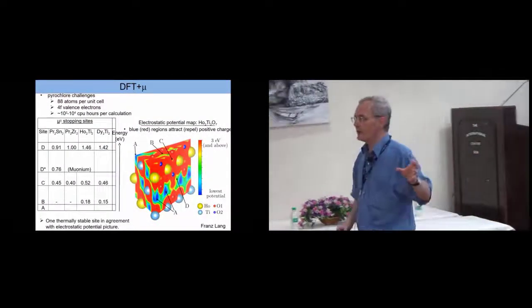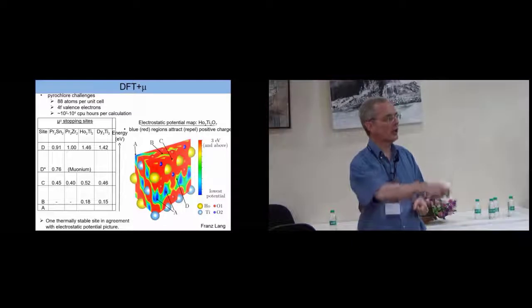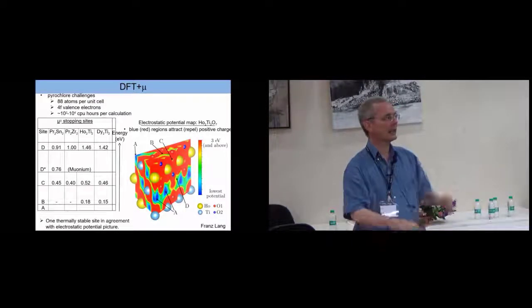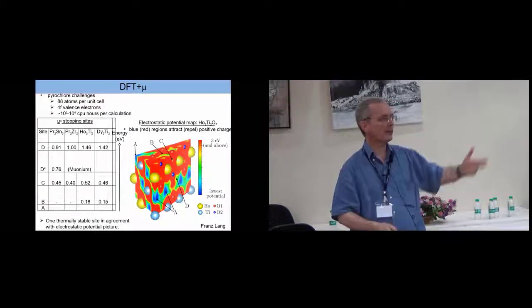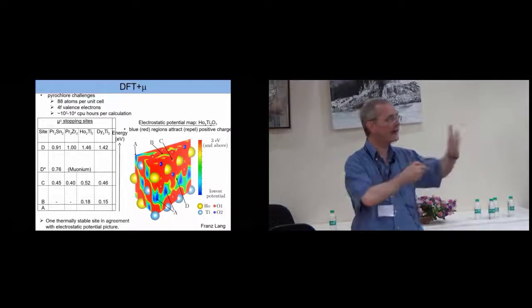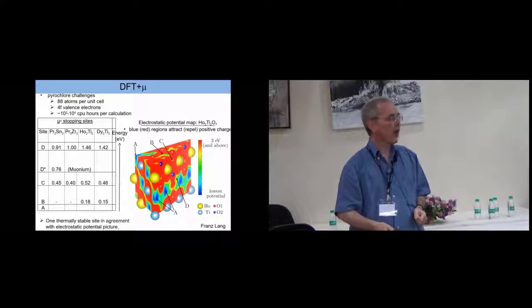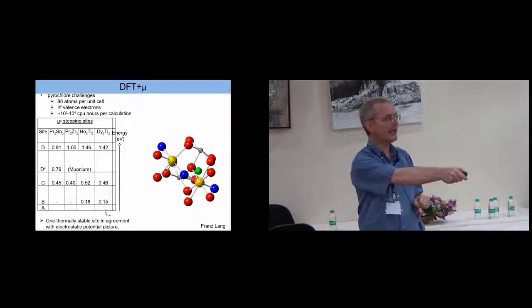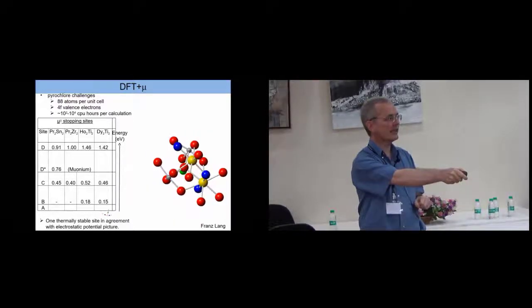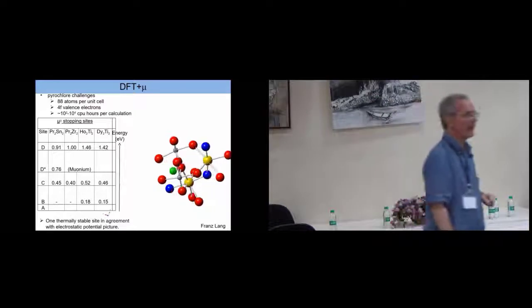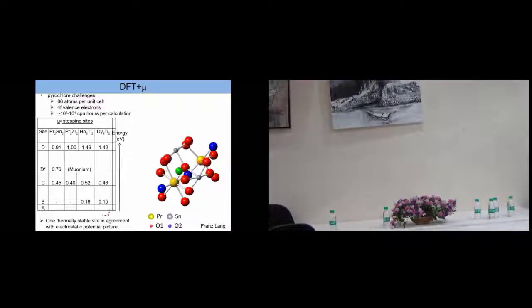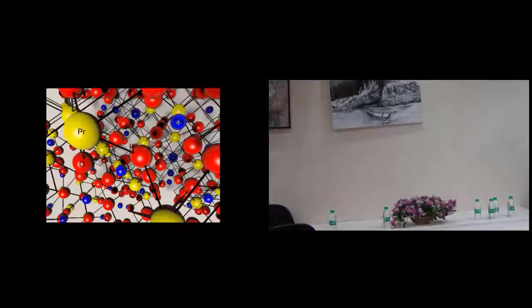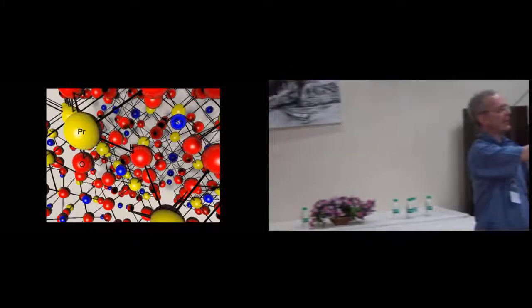Okay, so we did the DFT plus mu calculations to find the muon site. You do an electrostatic potential. That gives you some possible starting states, but then you have to relax the structure. I'll just focus on the final state. Here is the muon. It's this green in the lattice. But I think the next picture is a better way of looking to see what's going on. So here is inside the praseodymium stannate lattice.